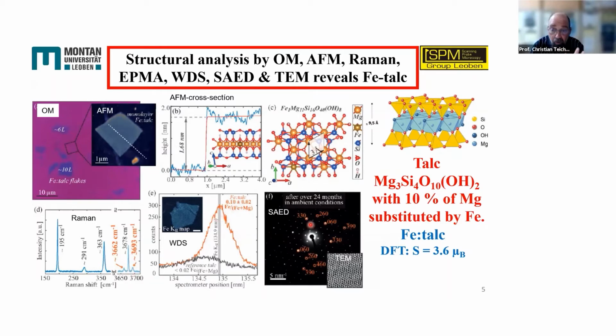So also selected area electron diffraction and TEM point to talc. We have talc, which is usually a phyllosilicate containing magnesium embedded in OH, so with an octahedral configuration, and then embedded in SiO4 tetrahedra. These SiO4 tetrahedra make the material air stable.